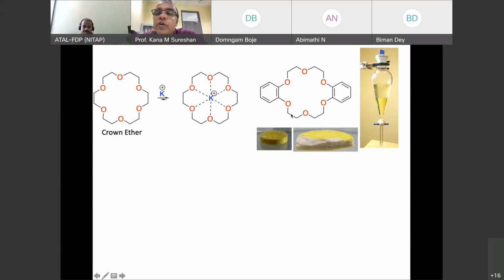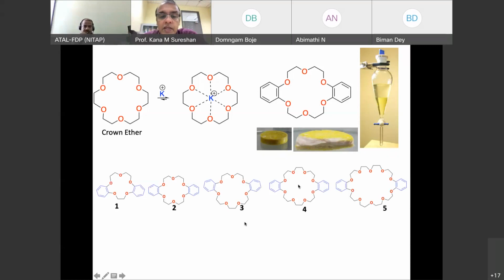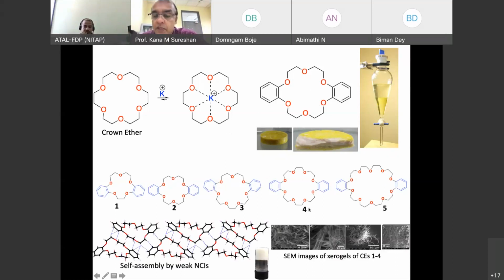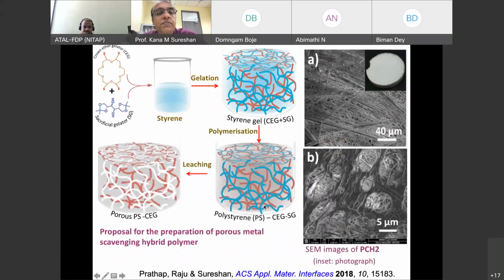So again, we want to make sure that this material is porous so that the potassium along with the water can reach inside and maximum efficiency can be obtained. So we thought we can use some gel chemistry. Fortunately, all these benzo crown ethers are gelators. We found them as gelators, and they form all kinds of fibrous structures, as I have shown here. This is the SEM picture.